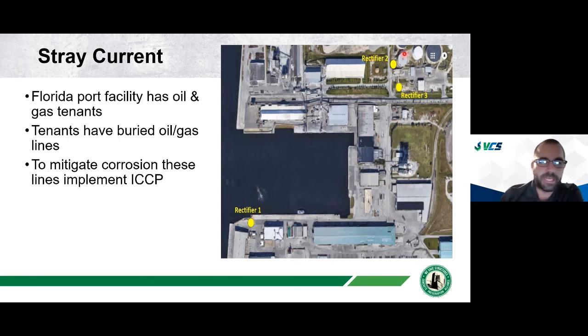So they have cathodic protection on their tanks. They have rectifiers over here that I've highlighted, but they also have cathodic protection on their pipelines, and they have a rectifier here. And the port was noticing that their steel bulkhead wall in the vicinity of rectifier 1 was corroding at extremely high rates. They were having to replace bulkhead walls every few years in this area and repair things, and they did not understand why. So we were asked to come in and see why there was such significant damage on this wall. We identified that there's a rectifier right here pushing current onto a pipeline, and nobody had done any analysis to verify that stray current was getting onto that wall.